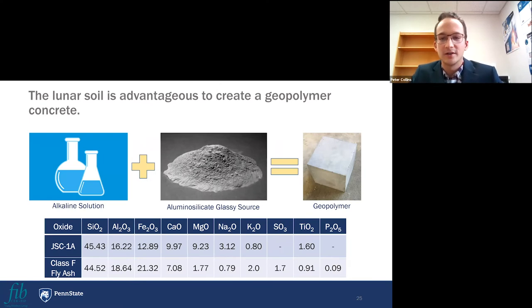This is where we get into my future work on the development of an in-situ lunar concrete. And right now we are working with a geopolymer concrete. A geopolymer is really a simple mixture. You need an alkaline solution such as a sodium silicate and sodium hydroxide combination, or you can use a potassium silicate. And then you need an aluminosilicate glassy source. This is often a fly ash or a fly ash and slag combo here on Earth. And when you mix these together, you get your geopolymer concrete.